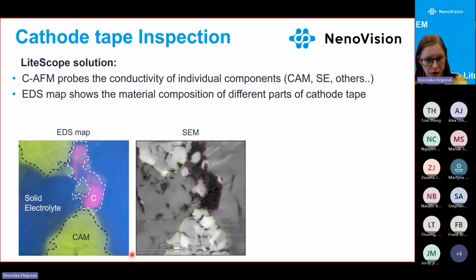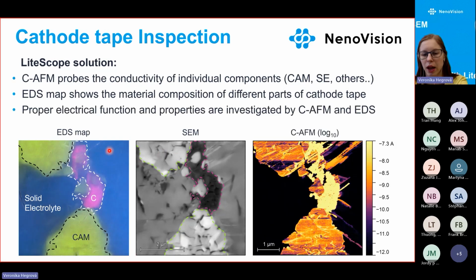We can see it in the secondary electrons. And further, we analyze the conductive AFM. And as we can see, the dark part is the solid electrolyte, and we are analyzing electronic conductivity. The solid electrolyte is mainly conductive ionically, so that is correct. Then we have a look at the cathode active material, which is conductive in some way,